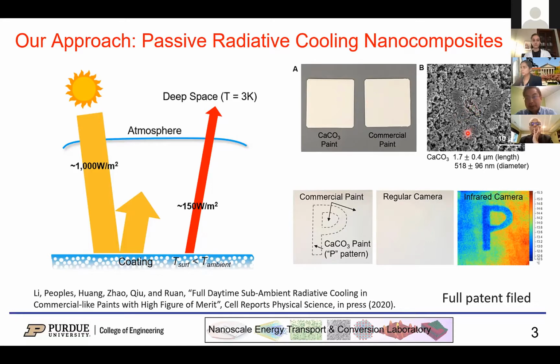We made the nanocomposite using calcite nanoparticles, which are very cheap, comparable to commercial paint. And this is the SEM image. You can see the particle size is in the micron or a few hundred nanometer range. We confirmed the performance by painting the P pattern. P stands for Purdue, actually, with our new nanocomposite, and the rest of the background with commercial paint. Under a regular camera, you don't see anything because they both just look white. But under an infrared camera, you can see the P is much cooler than the background. This means that we can really cool the surface. It can be cooled even below the ambient temperature. So you get free refrigeration.